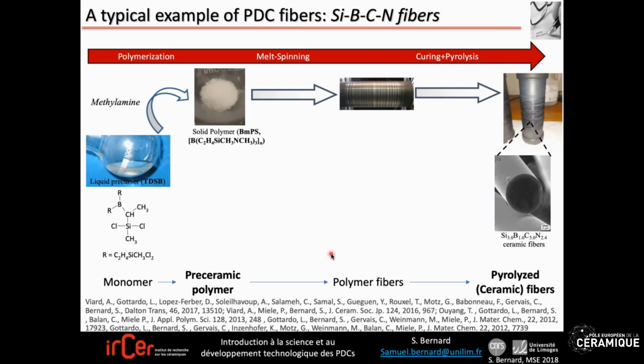So the fabrication of these fibers is probably the most complex in the PDCs field, because you should produce a polymer that contains functional groups that offer it fusibility, and you should stretch your fiber during the spinning to reduce the diameter of the fibers in order to reduce the quantity of defects in your fibers. Your polymer should be stable during the spinning with particular rheological properties, non-Newtonian, and a viscous component above the elastic one. Your polymer should be cross-linkable itself or with the atmosphere used during the curing, and it is expected to have a limited weight loss upon the pyrolysis.